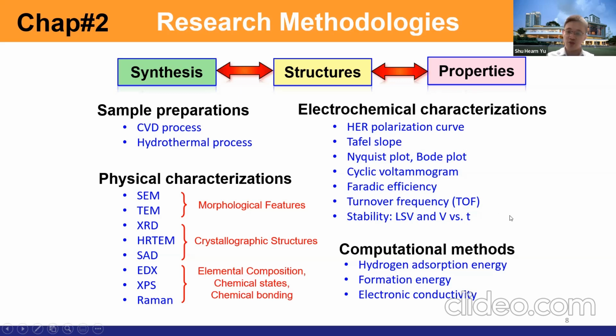For the formation energy, we try to see whether or not the dopant can be effectively doped in the material. If the formation energy is negative, then we can say that it is thermodynamically favorable for this dopant to be doped in the material. If it's positive, then you have to be very careful because, rather than being doped in, it could form another catalyst. You can have two phases precipitating out from a matrix. And then we also want to see whether or not the dopant can increase the electronic conductivity of our catalyst. So basically, this is the framework of my work during my PhD.